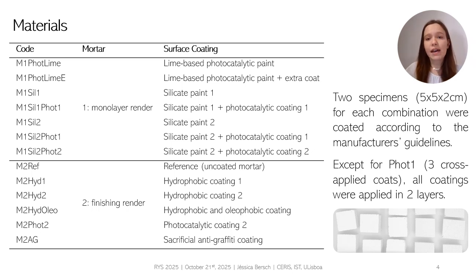Regarding materials, we have studied two different types of natural hydraulic lime-based mortars. The first one is a monolayer render and was applied with different types of paints. The first type of paint is a lime-based photocatalytic paint applied without and with an additional protective extra coating. Then we studied two silicate paints, both of which were applied with the photocatalytic coating 1, which is a commercial product recommended to be applied over the paint, and silicate paint 2 was also tested with photocatalytic coating 2 that could be applied directly to the mortar.